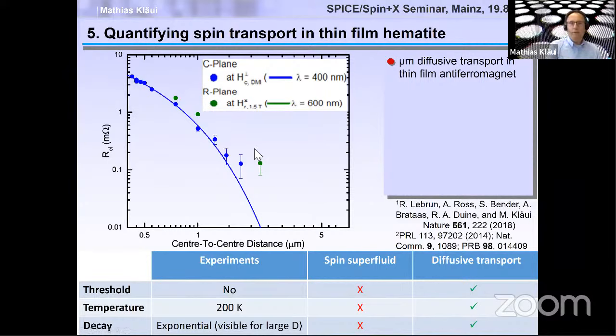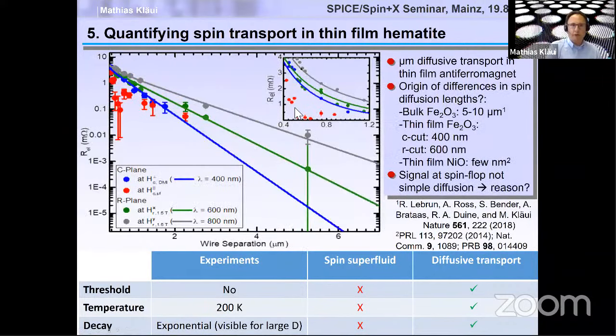And if we go close to the spin orientation transition, then we see that actually the spin transport length scale is not even dominated anymore by diffusive transport, but we see this very short length scale of just 100 nanometers or so where the spin signal decays. So there's not simple diffusion at the spin flop. And the question is why?